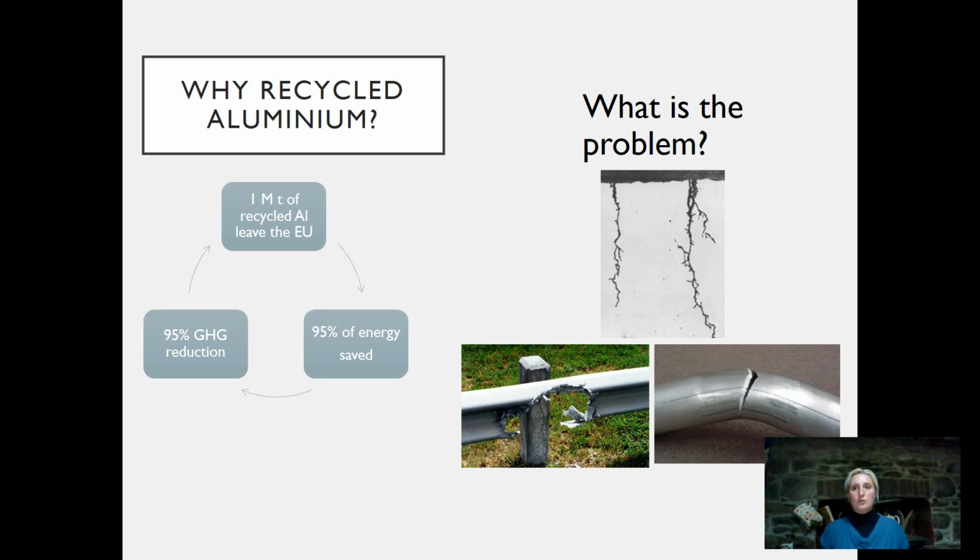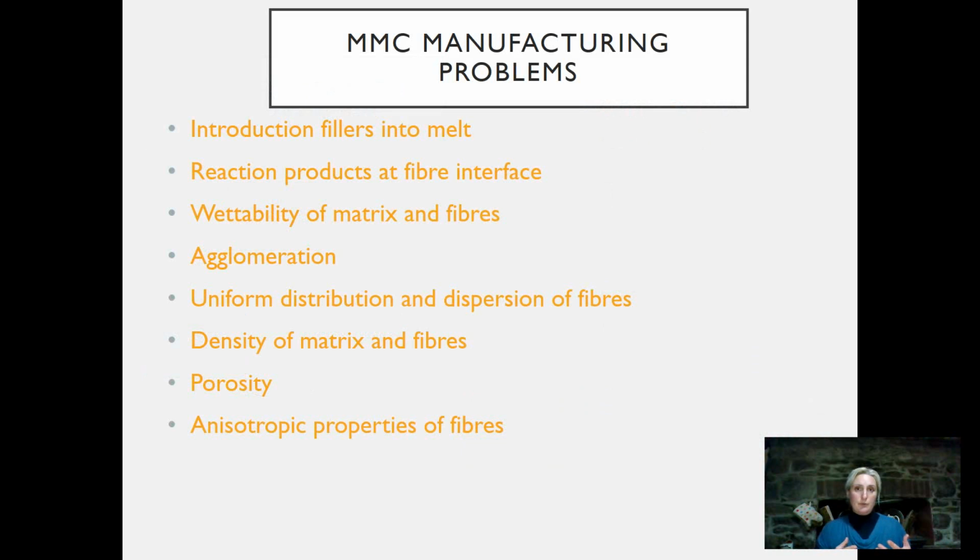So why is it we don't use it? Well, the problem lies in the formation of iron silicide. In fact, recycled aluminium contains contamination of iron. This iron combines with silicon and forms needle-like iron silicide called beta phases. These are actually the cause for cracking, poor corrosion resistance, and poor formability. So what we want to try and do is put the basalt into the aluminium and see if we can improve on these factors.